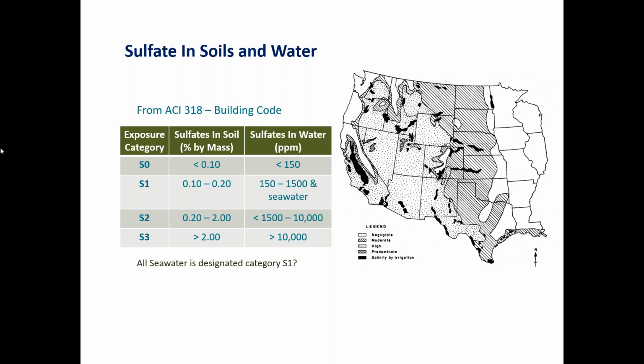And then as you go up through, you see that those numbers become larger and larger until you get to S3, which has sulfate by mass, and from what I understand, those conditions can exist. It seems very high, but in certain circumstances it can, and it's the most severe risk. And then sulfates in water at 10,000 parts per million or greater. And the one interesting thing that I like to point out, and I think it gets overlooked, is that you see that seawater is classified as S1.